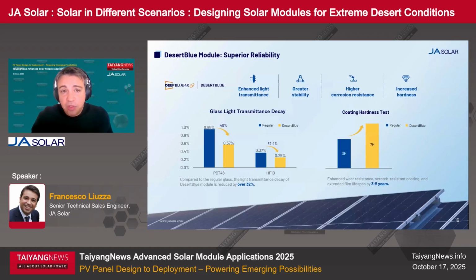In terms of reliability of the glass, we are showing here how the new glass has enhanced light transmittance, greater stability, and higher corrosion resistance. We performed several tests on models, so you can see on the left side a graph on glass light transmission decay, where the light transmittance decay on the DesertBlue is reduced by over 32%. You see some chamber tests, pressure chamber tests, and humidity freeze results, and for sure it offers enhanced wear resistance, where coating hardness tests show extended film lifespan of higher than 3-5 years.